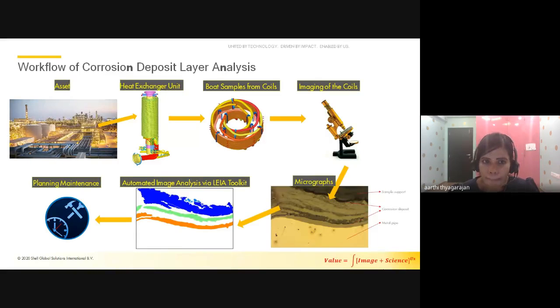It's a very big plant, at least equivalent to 7 or 8 Olympic field size. And this is the SEC coil that you see in the second picture in this workflow, a few meters in height. They're so big. Out of these coils, we take some boat samples, and from the boat samples, we try to come up with strategies for automatically classifying whether it's time to clean and prevent any leakage from happening. Because if we don't clean, the critical thickness will be crossed over, and the coil will start leaking because of what I explained, the wick boiling effect. Yeah. Next slide, please.